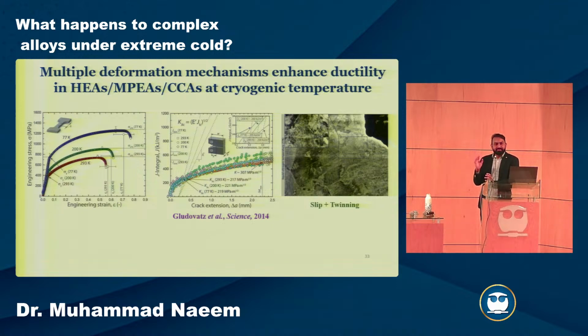Everything about deformation is related to dislocations. Dislocation movement becomes difficult, so they become less mobile. There are a number of other factors that I will not go into detail about, but the material becomes stronger at low temperature. Yield strength increases, but ductility usually decreases. Some materials even become brittle at low temperature. They have a ductile to brittle transition temperature. But usually FCC, face-centered cubic materials don't have that kind of issue.